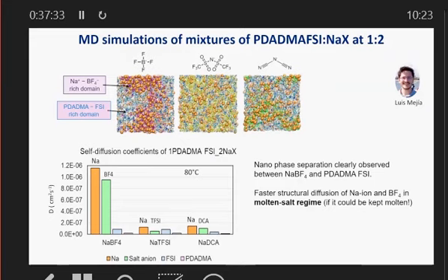And we fixed the ratio 1:2 because that's what seems to be optimum so far in various measurements that we've done for lithium and for sodium. What we found with BF4 is we got these nanoscopic, phase-separated domains, and we found them also in TFSI but to a lesser extent, and we found them in DCA but to a lesser extent. BF4 definitely had these domains.